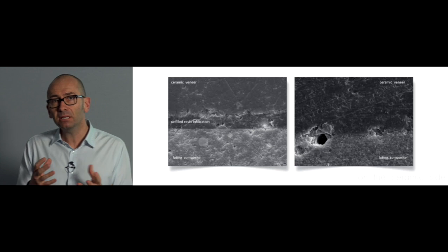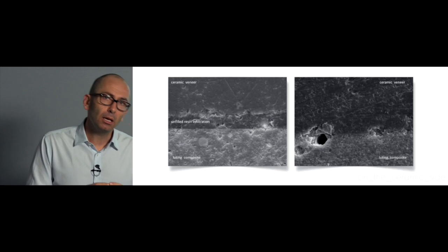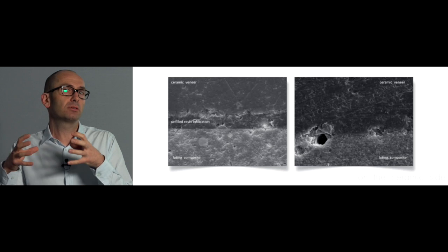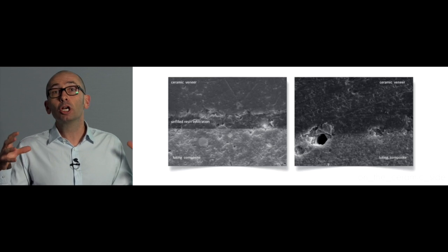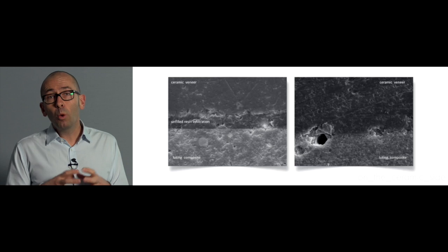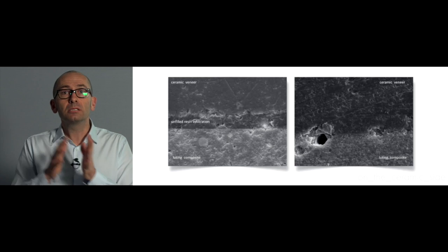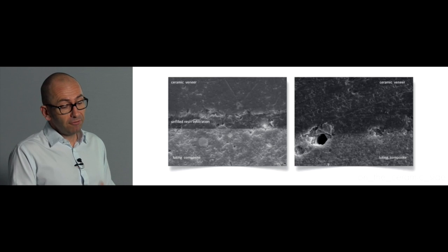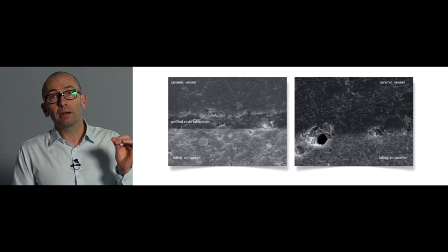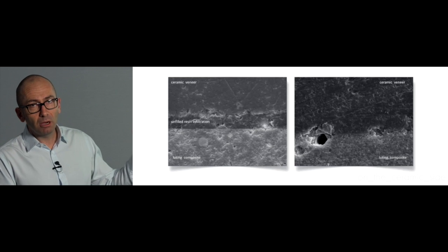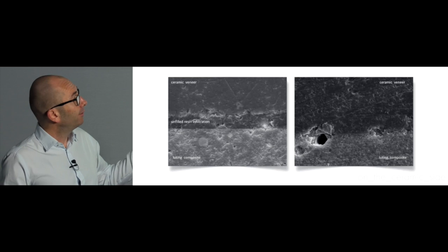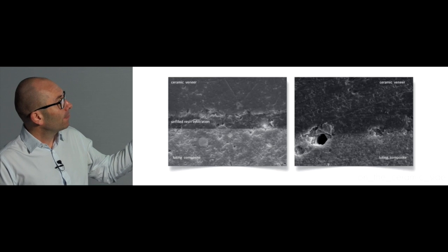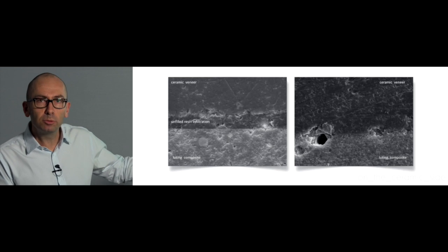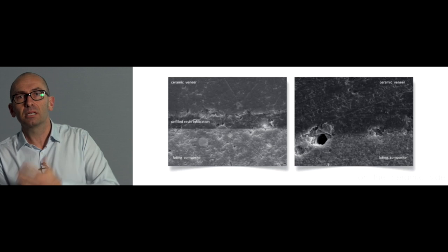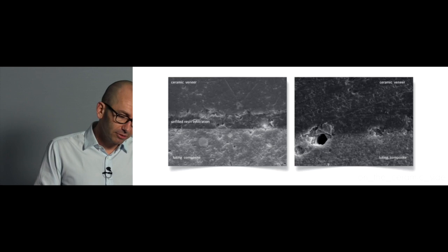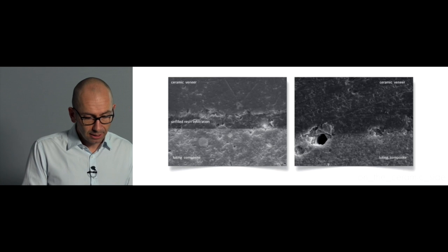Why? Because effective bonding and reinforcement of the ceramic are two concepts going close together. Once it's effectively bonded, it's strong. And if the resin comes inside all the irregularities, in all the flaws of the inner part of the ceramic, which are very often the initiation of cracks and of problems, you will improve your bonding, and at the same time you will improve the resistance of the piece, which is quite interesting, and we have to keep that in mind.